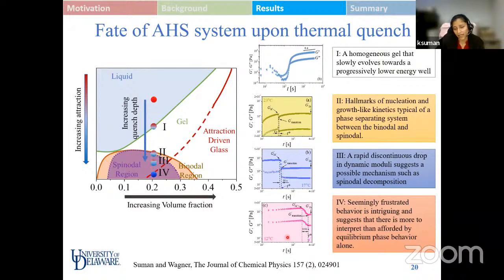Finally, when we are at very high quench depths, where the system is in a very arrested state, it takes a longer time for the system to transition, and therefore the transition becomes more wide and takes around 1000 seconds. It has entered into the deep two-phase region, which corresponds to the behavior shown over here.